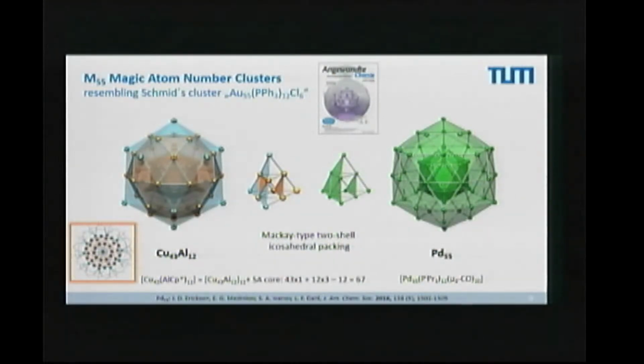So this nicely proves 2 things. It proves that the superatom, shell closing model is working in these systems, and it also shows that we have more reactive and less reactive clusters, and it also shows some clusters may be easier to grow or to add metal atoms, others won't. Now this is the thing you mentioned. This is the big copper 43 aluminum 12 cluster where we have all the coppers inside and the aluminums outside. And this is a so-called two-shell Mackay icosahedral cluster, and there is also famous reference compounds, because the metal atom count 55 is a magic number in terms of icosahedral shell packing. I skipped that. This is a detail for the crystal scientists and solid state chemists.